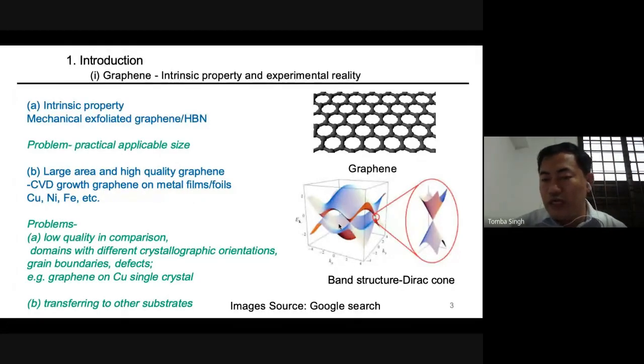I want to mention the positions of the high symmetry points in the Brillouin zone. Corners are called K points, the center of this Brillouin zone is called the gamma point, and the middle of this side is called the M point. We are going to study the band structure at these high symmetry points. If we look closely at this K point, we see that the conduction band and the valence band meet at the Fermi level, and the bands are linear. So this is the main source of the intrinsic property of graphene.